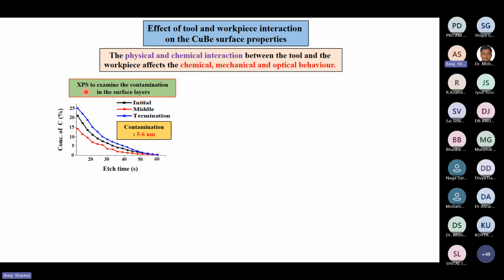XPS, X-ray photoelectron spectroscopy, showed that if we etch for some time, the percentage of carbon beneath the surface was more on the surface initially, and as we etch for a longer time, at about 5 to 6 nanometers there was some contamination of carbon atoms. So that means the carbon atoms from the diamond have diffused into the workpiece surface.